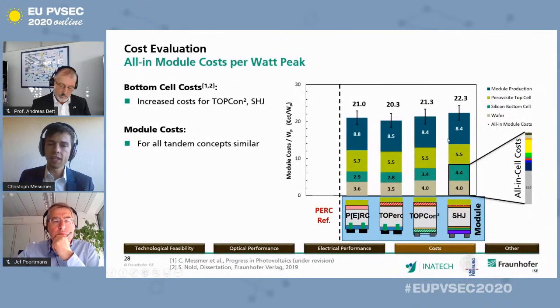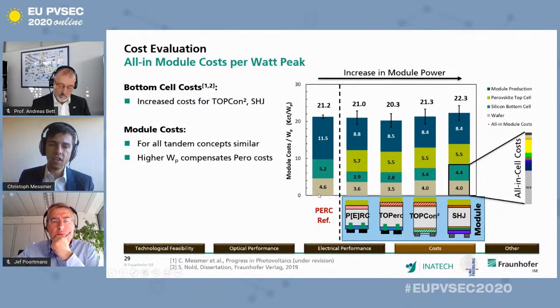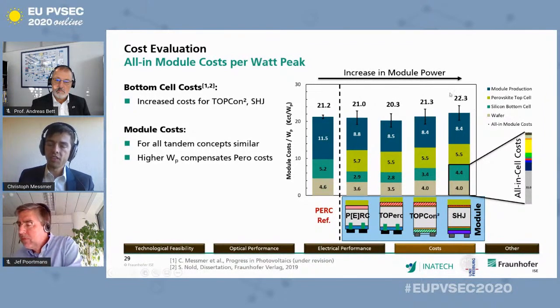You have to keep this in mind, because if we then compare this to the PERC reference, which is a single junction, we see that actually the additional perovskite costs for the tandem devices are compensated by the increase in module output power, so that in the end we end up to have similar costs for the tandem devices than for the PERC reference, which is a single junction, within the uncertainties of our model.